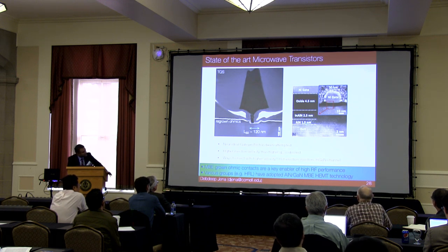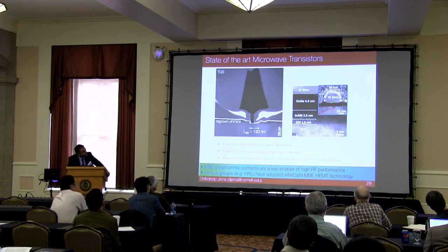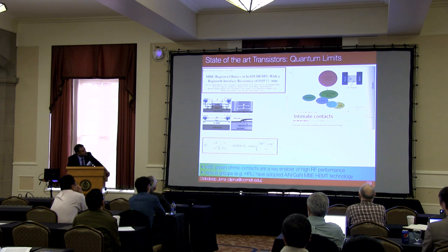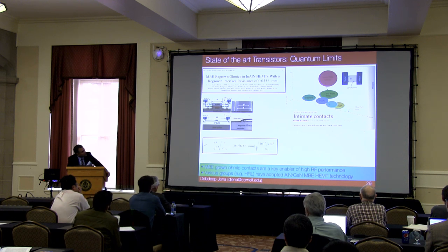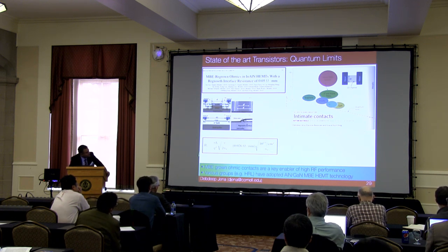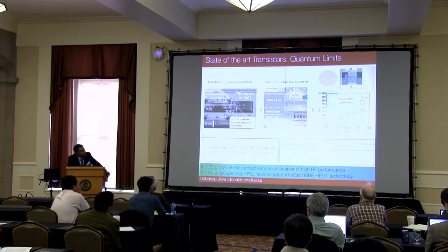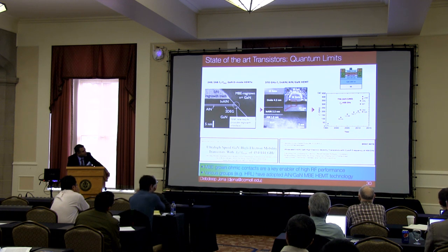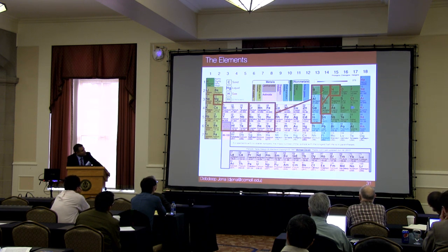One of the nice things you can do, I'll maybe skip over there, this is the 2D electron gas again that's grown on the superconductor, and we can push it into a very clean quantum Hall effect, very, very clean, n equal to 1 quantum Hall. These are when the 2D electron gas gets pushed out to the edge of the mesa, and these are completely topologically protected, so your Rxx is really zero, Rxy is exactly the quantum of conductance, 25.8 kilohms over n. N is 1, 2, 3, so you have one edge state, two edge states, and so on. So there are some interesting things one can do by combining superconductor and topologically protected edge states. That's a whole other game, but I think there's a good platform for trying those things out, potentially. We can even push this 2D electron gas into a fractional quantum Hall state, but anyways.